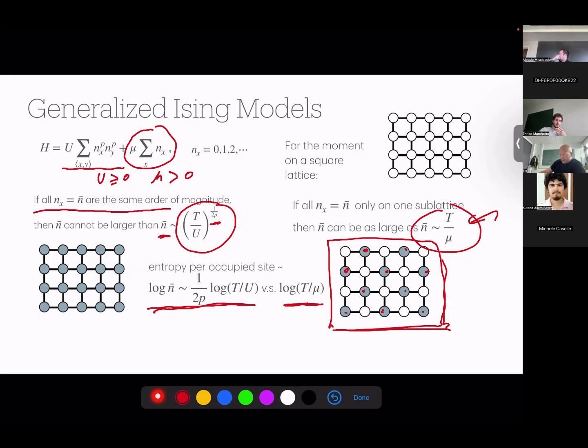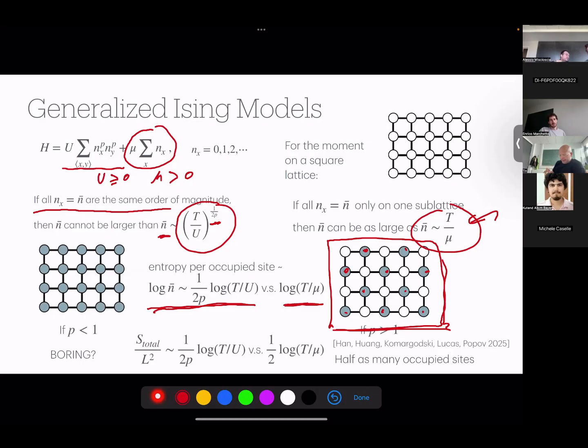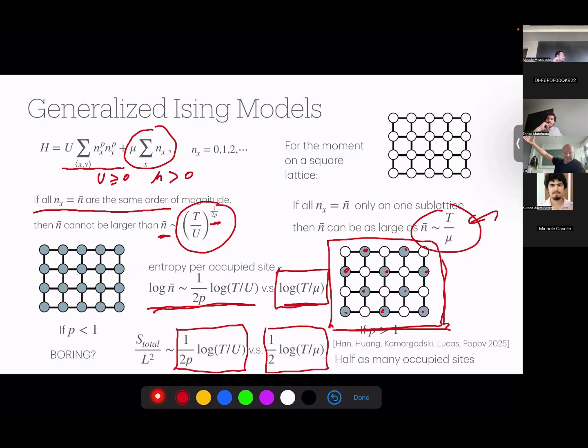Okay. If there are no questions here, let me move on. So that's the essence of why these models potentially have entropic order. Now, the only thing that you have to account for here is, of course, that in the right-handed case where there is some order, there's spontaneous breaking of translation symmetry, I have half the occupied sites. So per occupied site, the entropy is log t over mu on the right-hand side, but half of the sites are empty. So the total entropy density is 1/2 of log t, versus on the left side, I have 1 over 2p log t, right? And I'm taking temperature to be very large, okay?